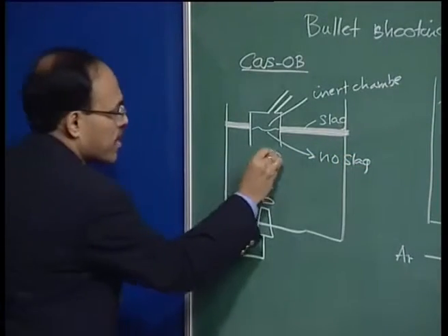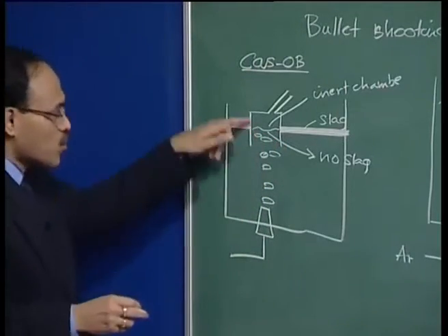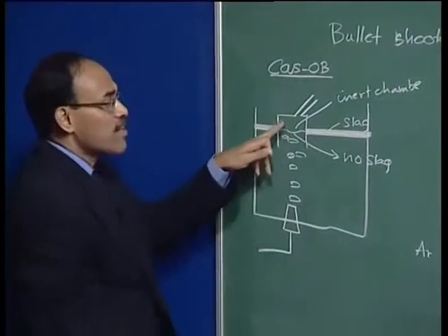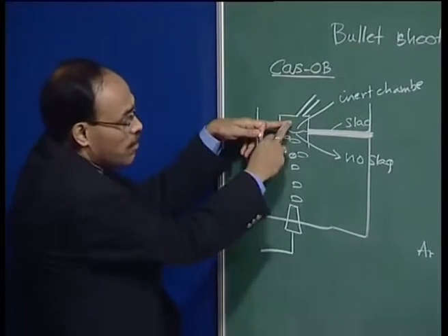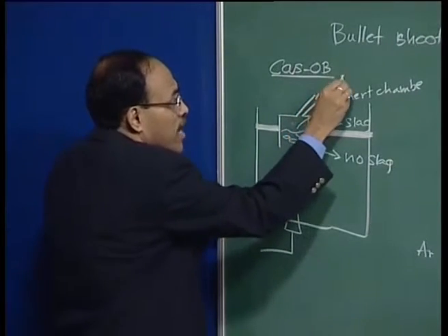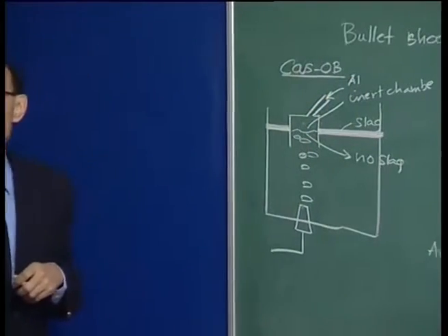So therefore the bubbles rise here within the central part. There is large velocity there because the gas is rising through this snorkel. There is an inert atmosphere here. There is no oxygen because the argon gas is going to be there, and through this chute alloys like aluminum, etc., are going to be introduced into the melt.